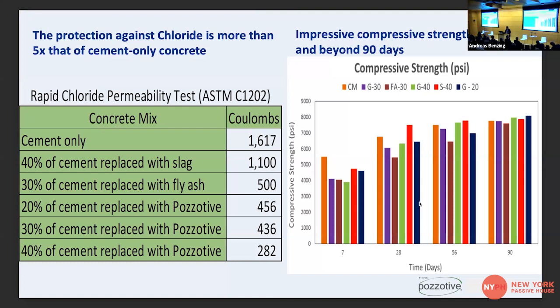This measures the rapid chloride permeability, ASTM 1202, and it's an electric charge that goes through a beam made with a batch with ground glass pozzolan. It just shows what cement only is, and the lower the Coulomb level, the better the resistance is against chloride ion attack. So why is that important?